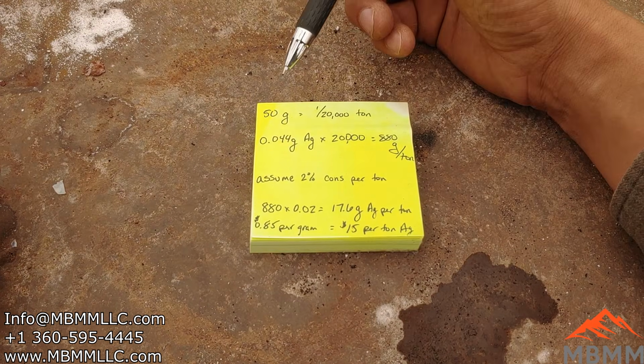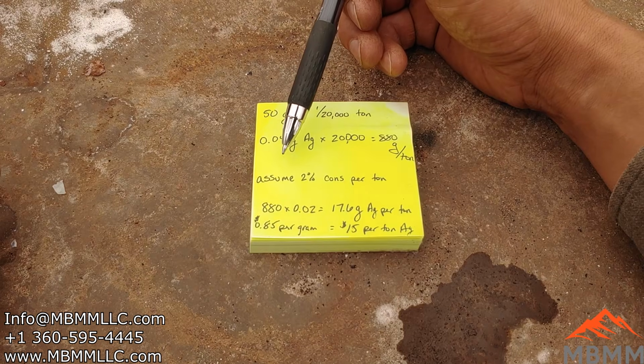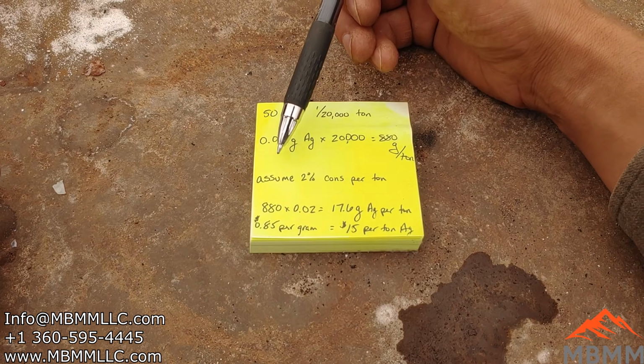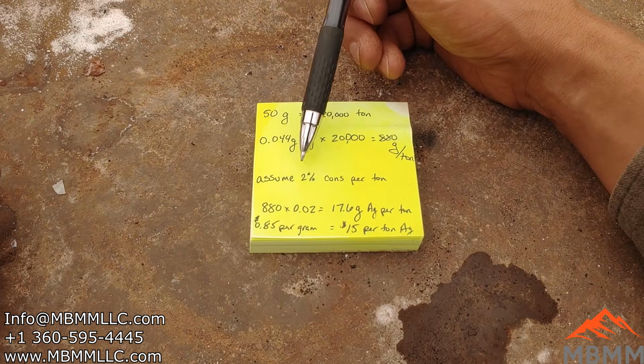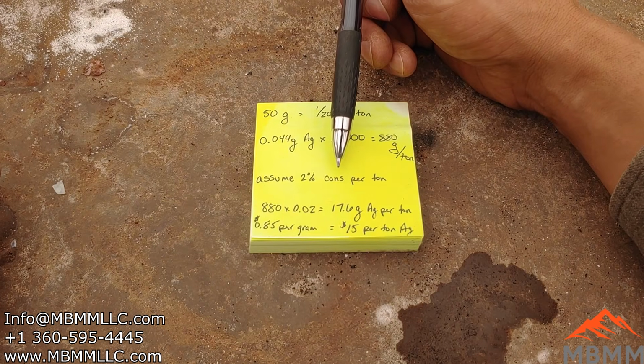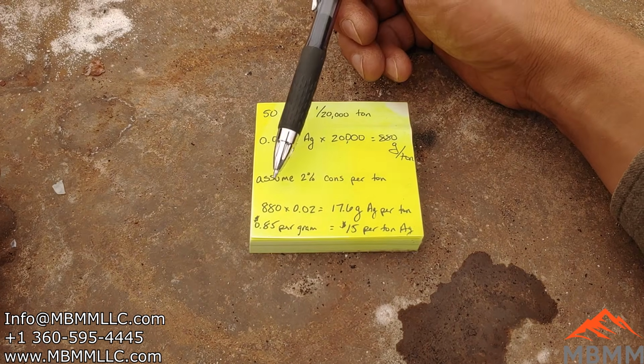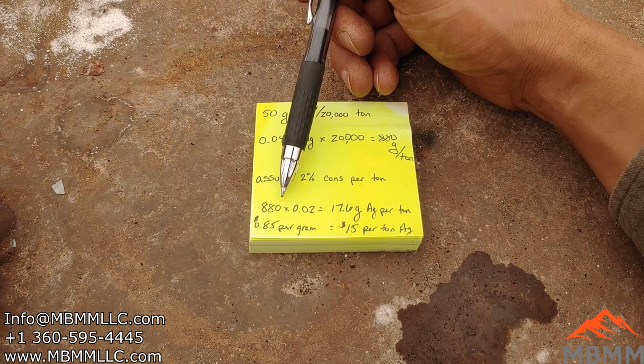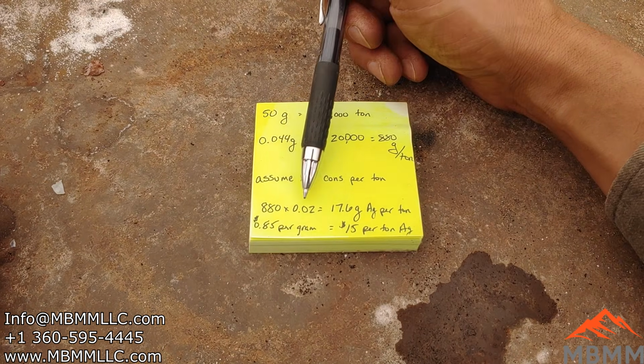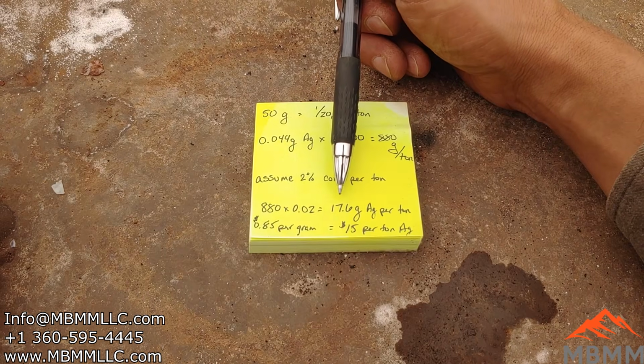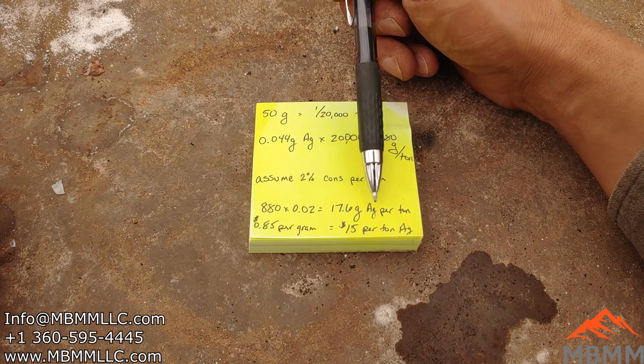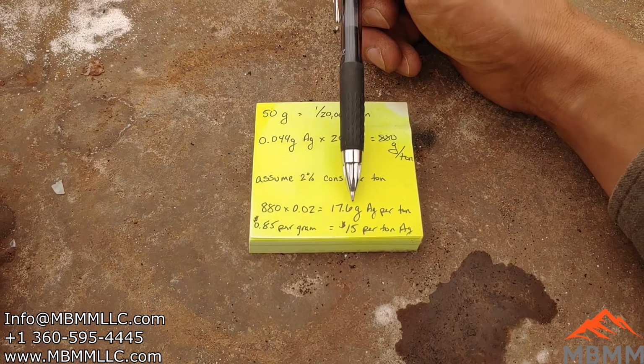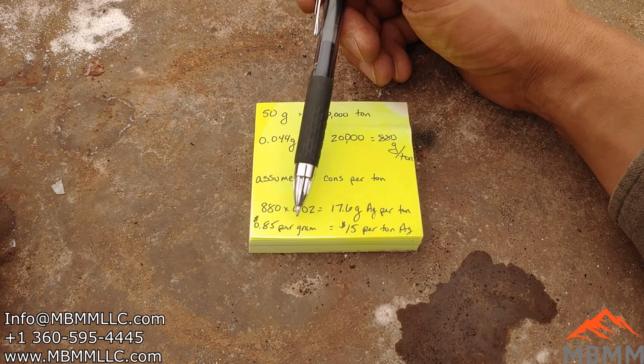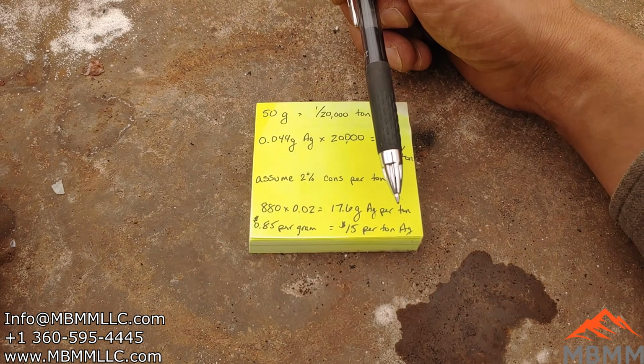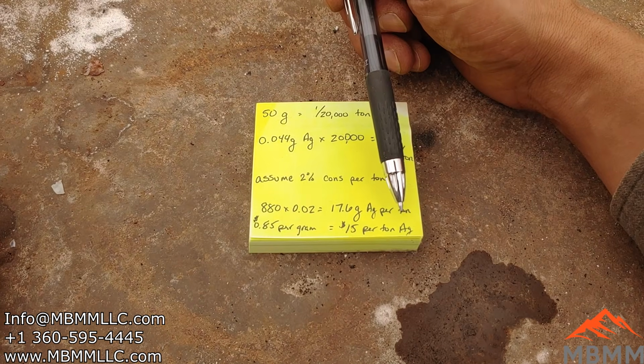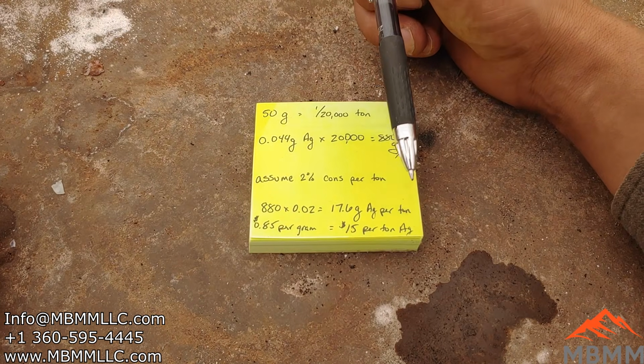I don't know the exact weight of the material we ran or the weight of the cons, but I'm assuming that, let's say you run a ton and 2% of those ends up being cons. So you multiply the 880 grams of silver per ton of cons by 0.02, and we end up with 17.6 grams of silver per ton, about half an ounce. At 85 cents per gram, there is $15 per ton of silver in that ore.